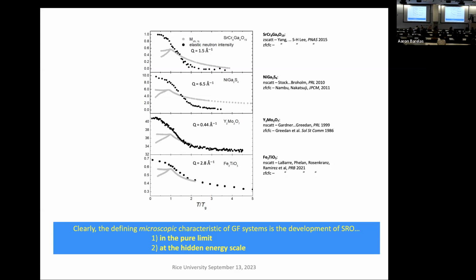Silicon is... Exactly, and silicon can be made at ppm levels of purity. These materials are probably at 1% or slightly under 1%, or 0.1%. But bear in mind, you can get spin glass behavior in copper manganese with something like 0.001% manganese. It's hard to measure because it goes down to very low temperature. But it's that long-range interaction. That's the thing. Yeah, I'm going to get there. That's what I said, the long-range interaction. So how does this happen?